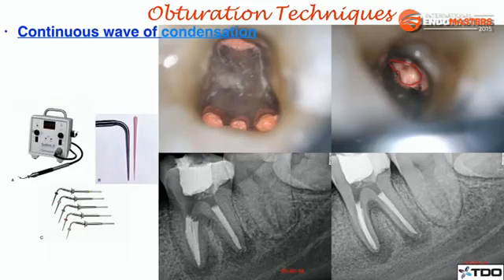It should be noted that in the continuous wave technique, the heat source is placed only within 5 to 7 millimeters from the tip of the gutta-percha. The apical portion of the gutta-percha remains essentially a single cone technique, as the heat transfer does not take place in the apical 2 to 5 millimeters of the gutta-percha. So one way to contrast this situation is to use a plugger that will allow us to go to within 3 to 5 millimeters of the gutta-percha tip.